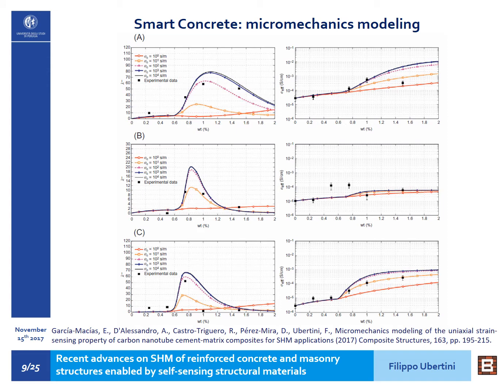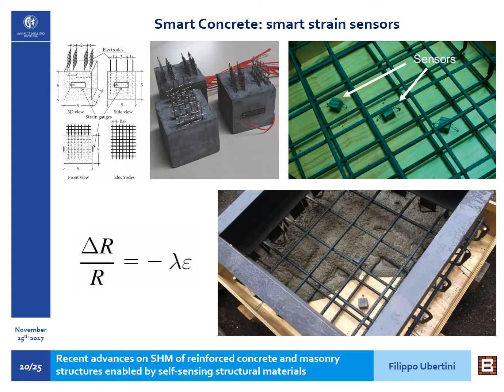So what's very important from this result is that both theory and experiments confirm that there exists an optimal amount of nanotubes that corresponds to a maximum gauge factor of the material, and this optimal amount of nanotubes is close to the percolation threshold. It's also notable that the theory can interpret quite well the experimental results.